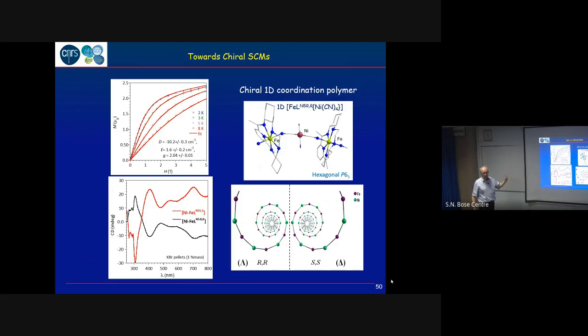When we started this project, we also did high field measurements, just to confirm that magnetization was in line with what we get from high field measurements. And now we know that this is easy to make. This works very fine, and we know the values we get. But once the fitting is not good, there's something else. And often in literature, you see fits that are not very good. So it means that the values that are given are questionable.